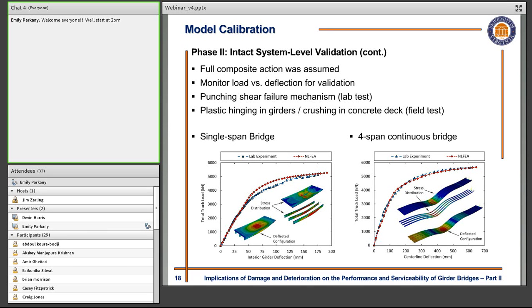And that can be attributed to the fact that these girders in this specific test specimen were built-up girders, and there were a significant amount of residual stresses which we were not able to include into our models because of the limited data they provided us on the amount of these residual stresses or on the welding procedure that they used to make up these girders. Other than that, on the second case, the 4-span continuous bridge superstructure, where we had rolled shaped plate girders, we didn't have this problem, so we had a good correlation between the elastic behavior and nonlinear region of the response of this specific structure.